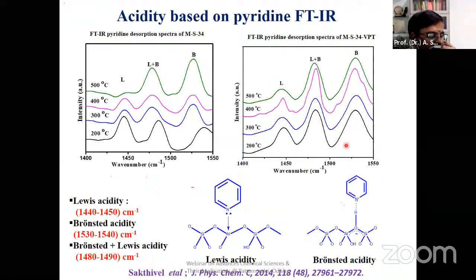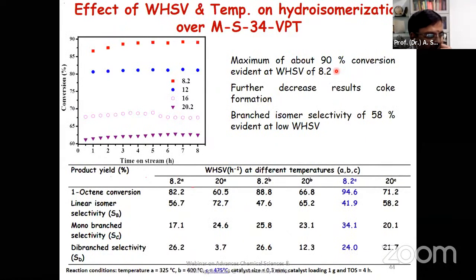So once we improve the silica treatment, we can see that the Bronsted acidity is improved quite a lot compared to the previous case. Once we improve the Bronsted acidity, we can see the overall branched isomer selectivity, here is the mono and the di branch. Overall branched isomer selectivity can improve up to 60%. That means you are improving the branched isomer selectivity and the conversion by improving the acidic strength.